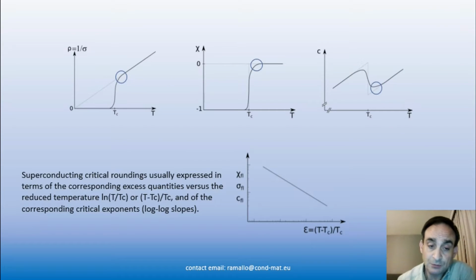So what we mean by superconducting critical roundings or critical fluctuations is the effects near the critical temperature that appear in many observables that produce roundings or excess quantities due to the proximity of the transition. And this can be seen in electrical resistivity, magnetic susceptibility, heat capacity, and other properties. And of course, they are usually characterized in terms of critical exponents, which are the log-log slopes, when represented as a function of reduced temperature.